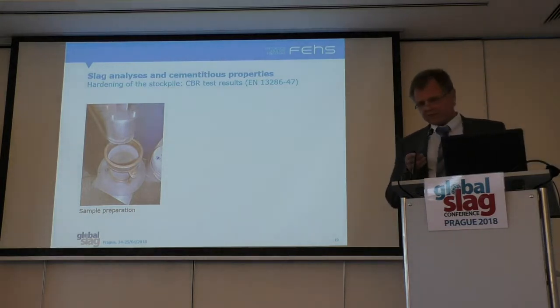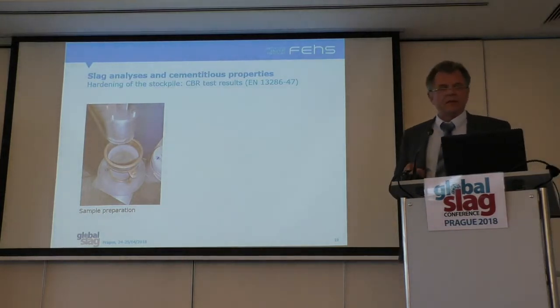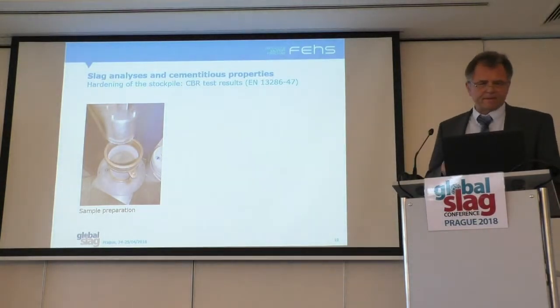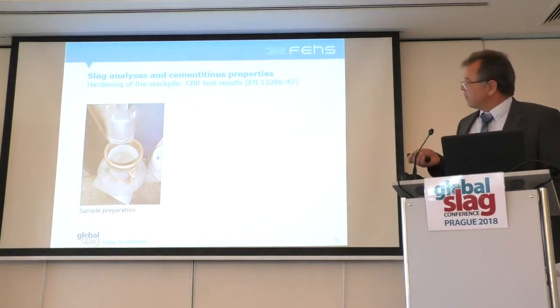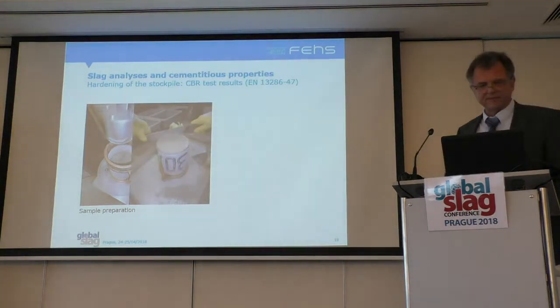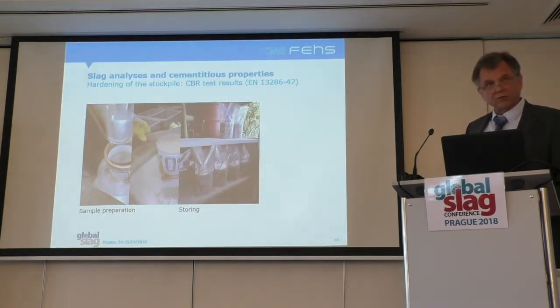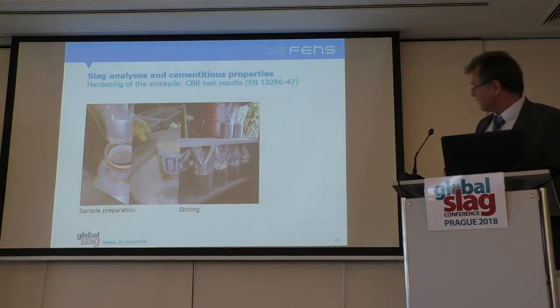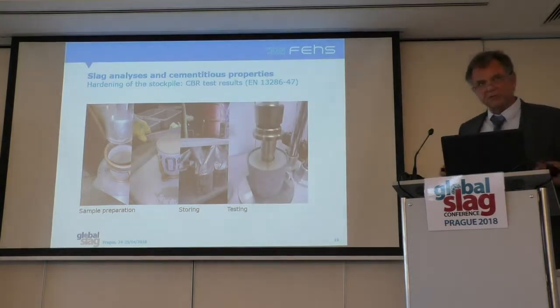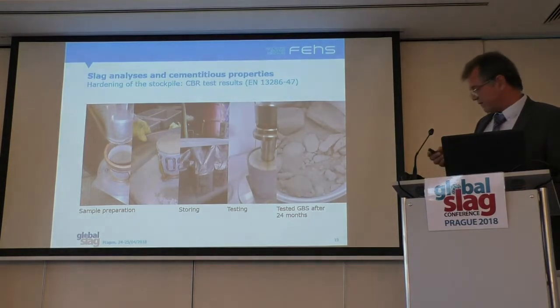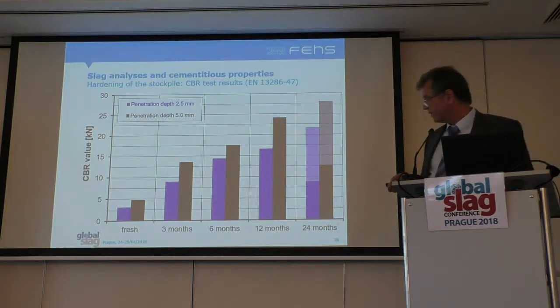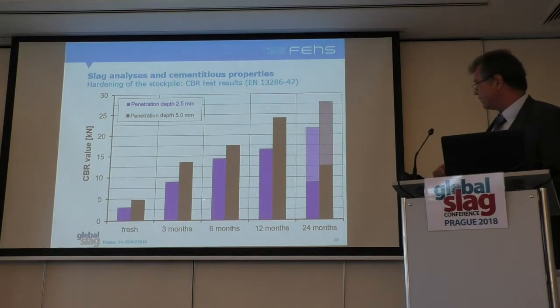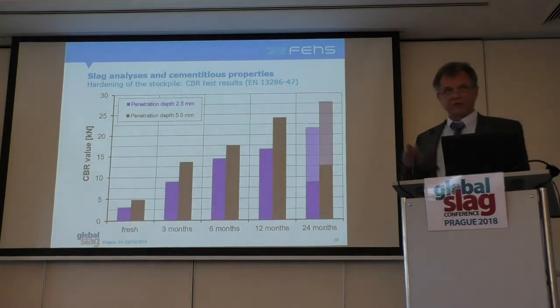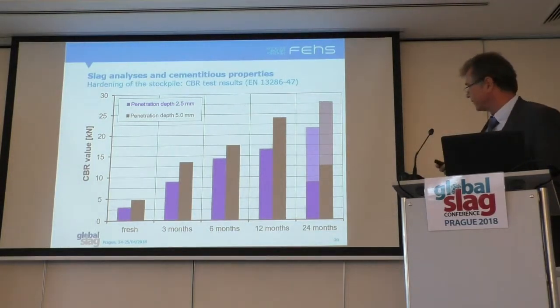To follow the hardening process, we produced CBR test specimens, proctor samples, prepared with unground slag with a certain moisture, protected against water loss outside, and tested from time to time. And that is a sample after 2 years. The values follow clearly the hardening process outside, which you could recognize in the pictures in the beginning of the presentation.